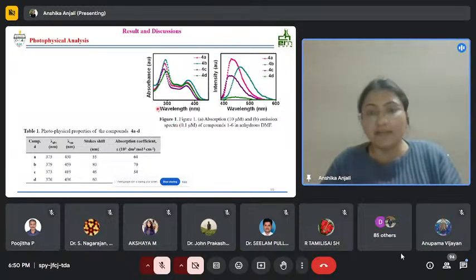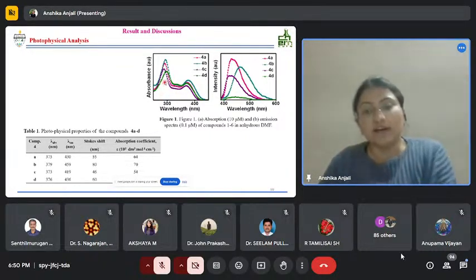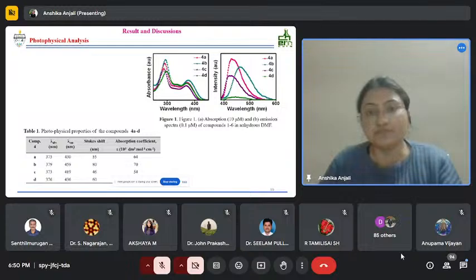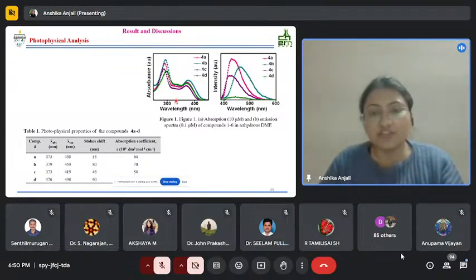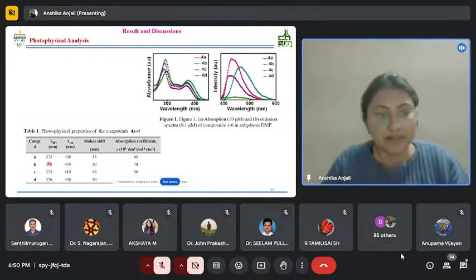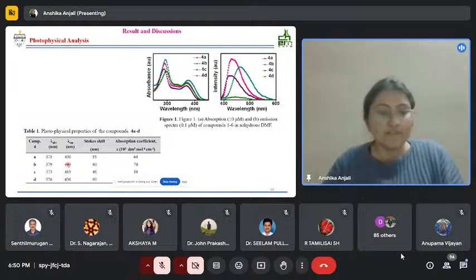We have obtained two peaks in the absorption spectra. This is a sharp band and this is a shoulder band, which corresponds to the pi to pi star transition, and the lower energy band corresponds to the n to pi star transition. The emission spectra were also recorded, and we have calculated the Stokes shift values as well. Compound 4b here, with the 4-methoxyphenyl group, resulted in a higher Stokes shift and a higher absorption coefficient.